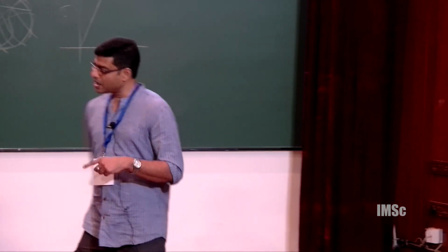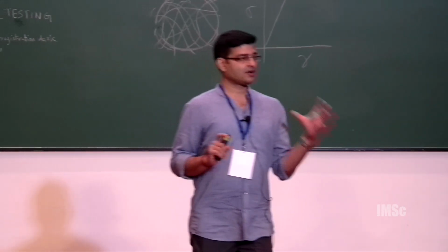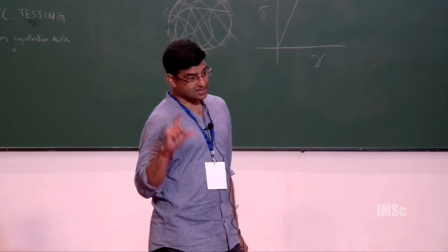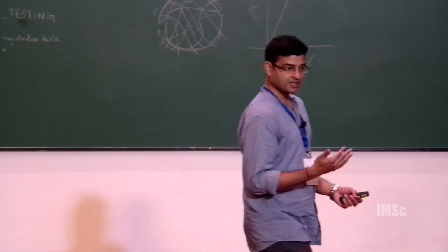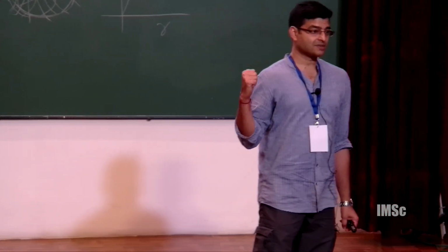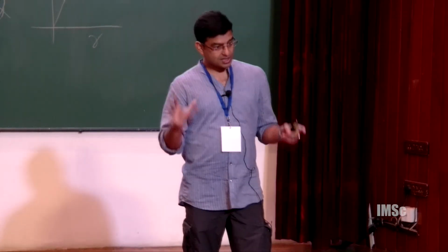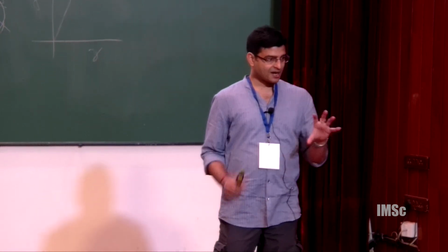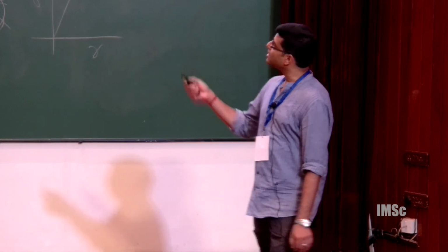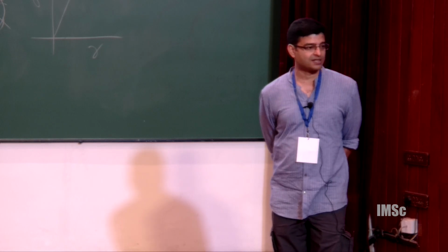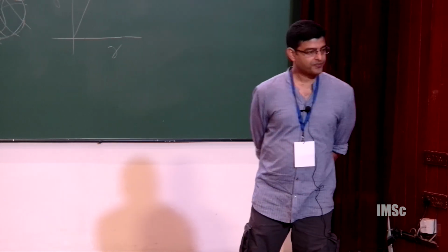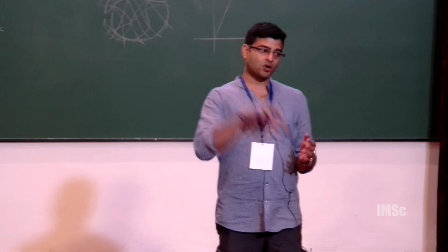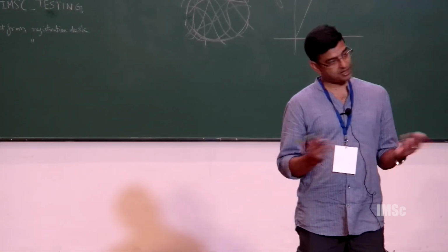Now how we mix the tracer particles, you are right, on this glassy sample it is very hard to mix the tracer. But what we do is mix the tracer particles first in the liquid, which makes a very dilute solution, then you gradually add these particles, so that ensures that it is uniformly mixed. Because with a glassy sample, if you try to mix, you will find that locally there are more particles, some fewer, and you need a uniform coverage for a reliable PIV analysis. Yes. But in liquid, if you mix it, then it becomes uniform, and on top of that, you form the glass. So then it remains uniform.